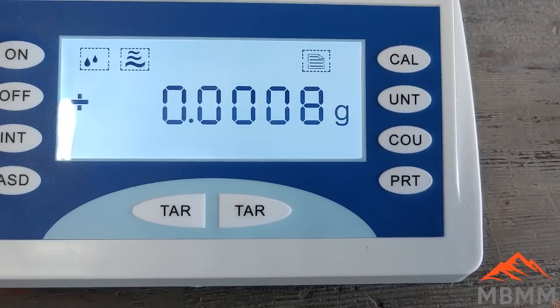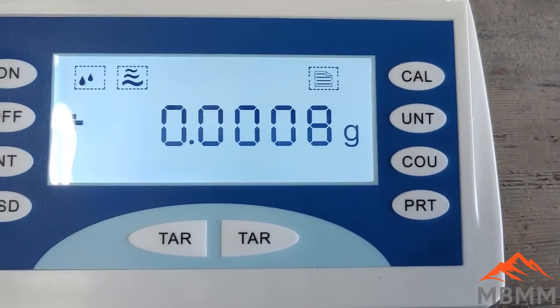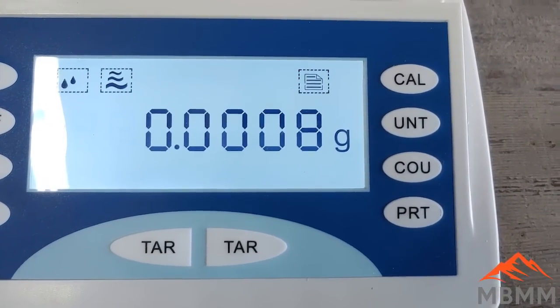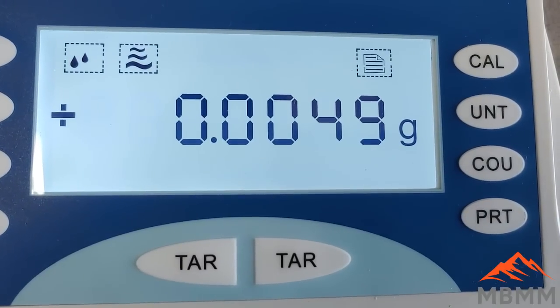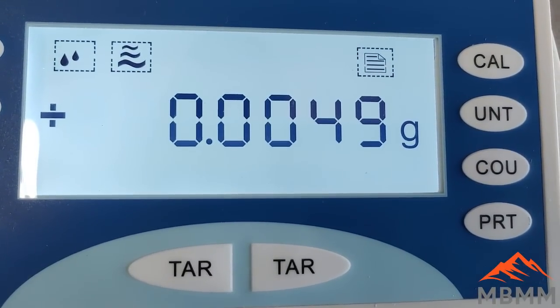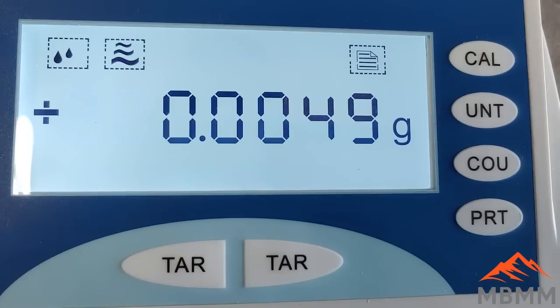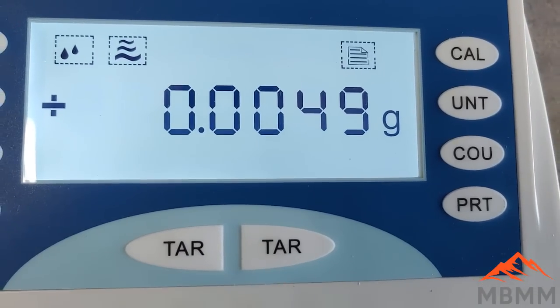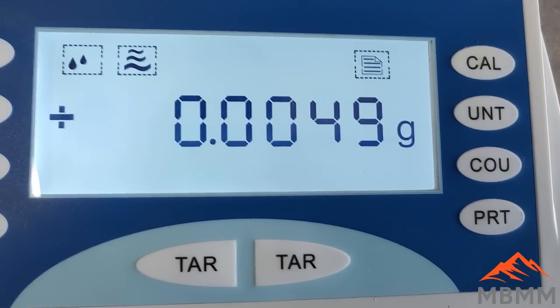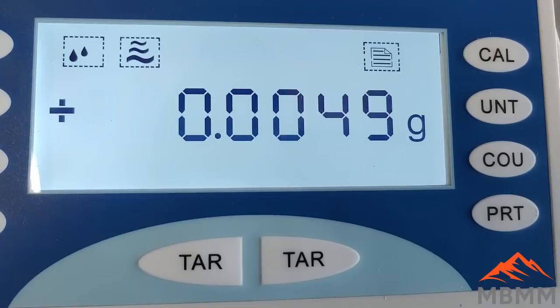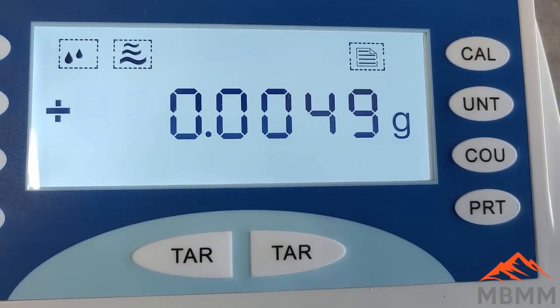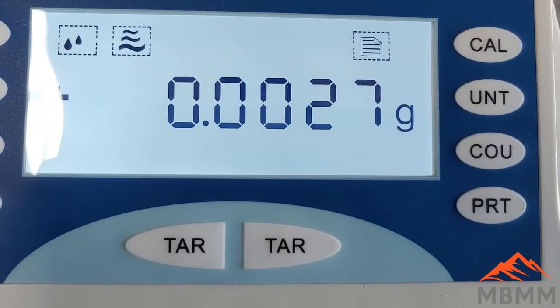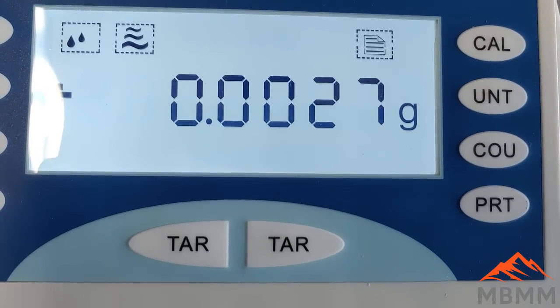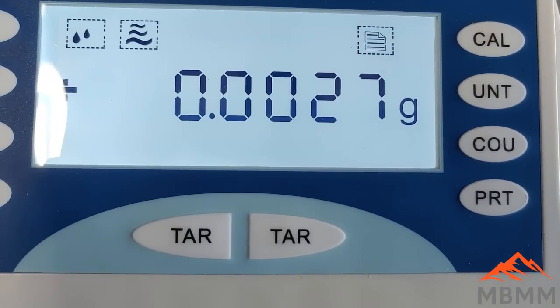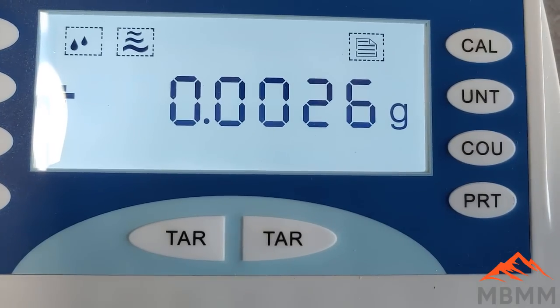Okay, so our residual silver in our collector metal weighs 0.0008 grams. And our button from 100 grams of our number 3 concentrates, our middlings, weigh 0.0049 grams. And so we got to subtract our 0.0008 grams from that. So we really have 0.0041 grams. So the bead from our tailings is 0.0027, but we'll subtract the collector metal off there. So we really have 0.0019 or 18.